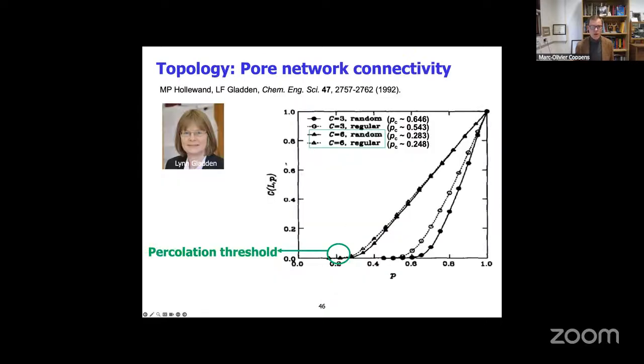But going back to Lynn Gladden's work, what she showed here is that both for random or regular networks, if the connectivity is high enough, and that's even in the case of connectivity of 6, so a cubic network, you get similar results, except if you're really close to that percolation threshold. Now, if you go to a connectivity, on the other hand, of 3, so much less connectivity in the system, perhaps because this is a porous catalyst that gets deactivated, or there are structural changes due to solid reactions, then things start to become different. Whether you are random or regular plays a role, and you clearly have a much more impact on the overall conduction property. So what is a good enough model will depend on your situation, or how connected your pore space is.